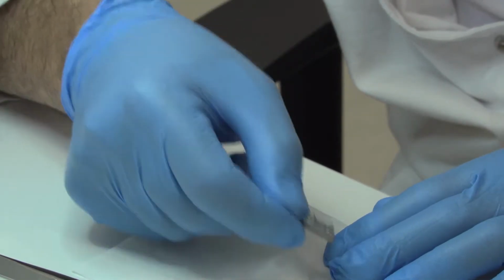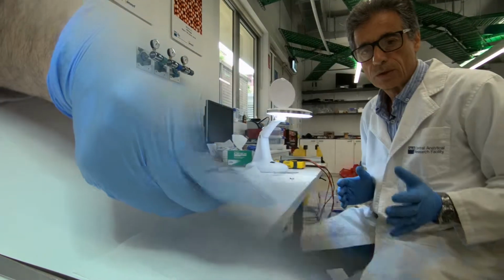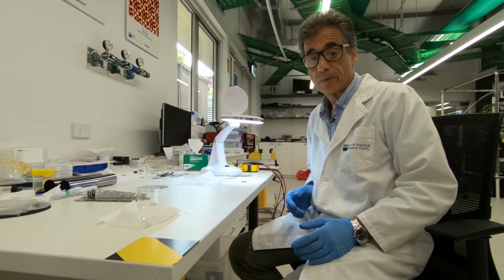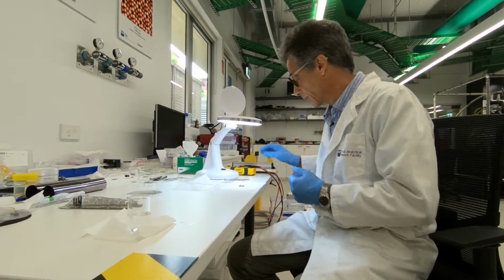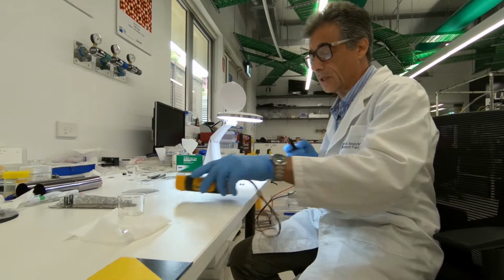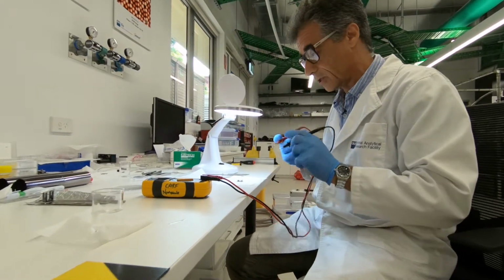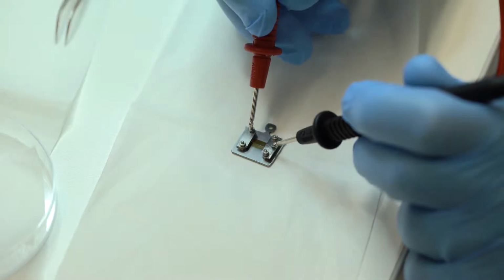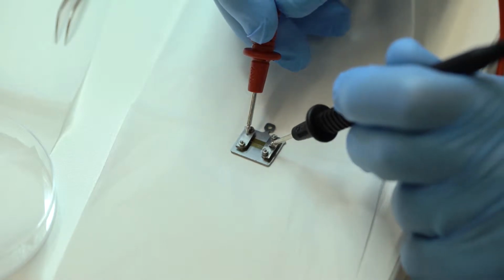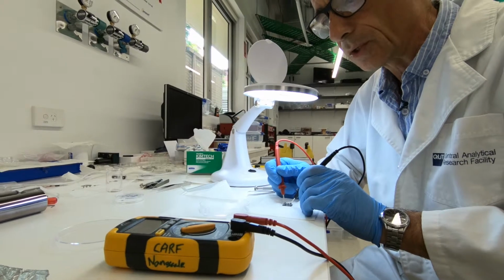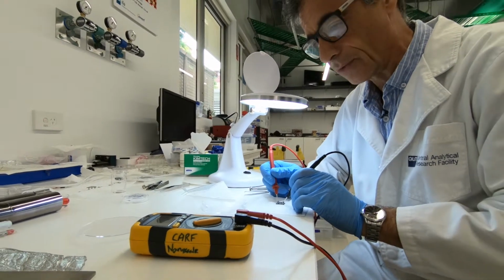Yes, it's well attached. Okay, now we are going to check the resistance of the sample because we need to pass current through the sample, and we want to make sure that the resistance is in the right range. So we are going to use this ohm meter, and we measure the resistance between the 2 ends of the sample, and it should be in the order of a few hundred kilo ohm.